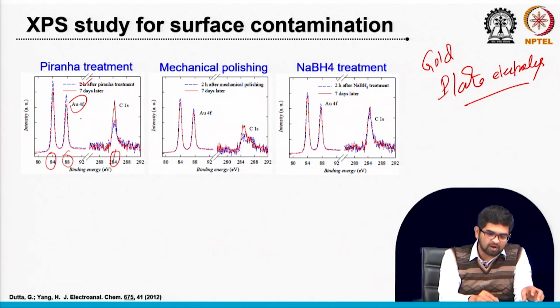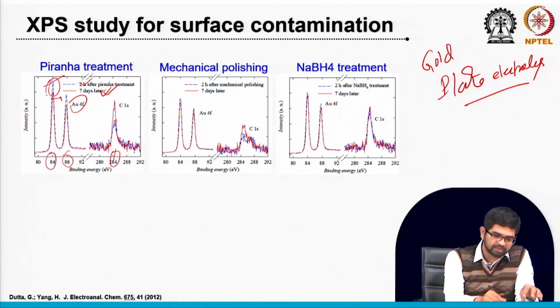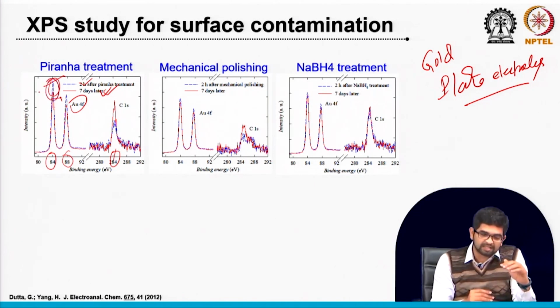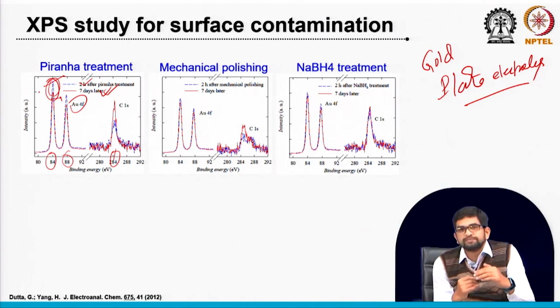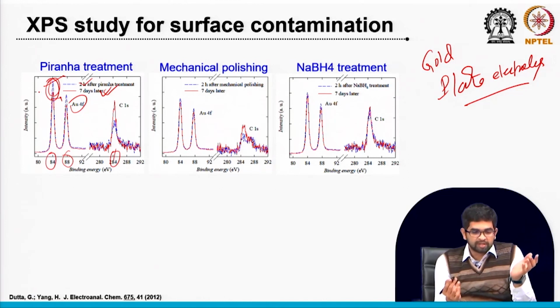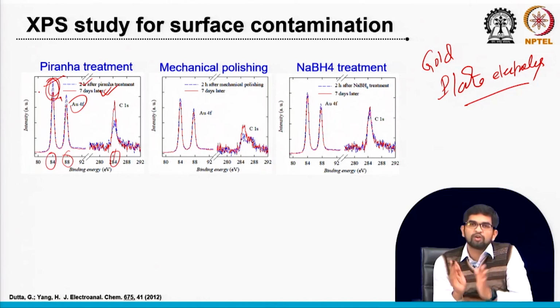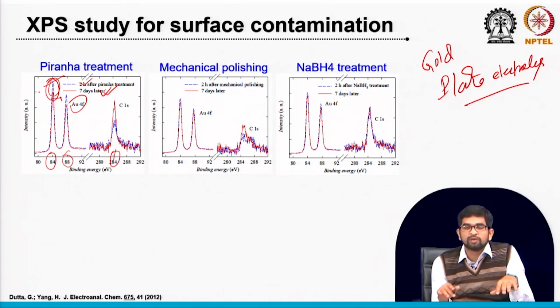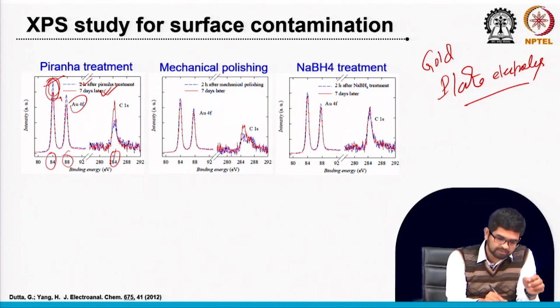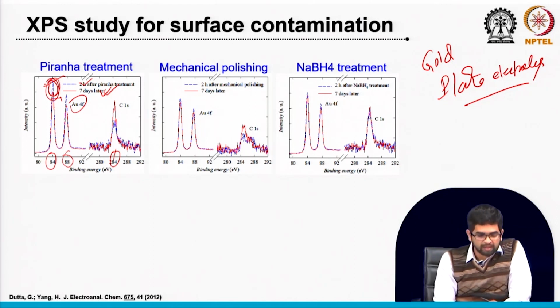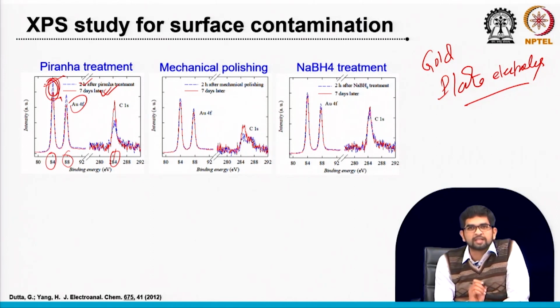You can see there is not that much change, but a little bit of change is still there after 7 days. Just after and after 7 days, you can see the gold peak decrease, right? It means the gold peak is covered, maybe some contamination is possible, because piranha treatment is a very strong cleaning method. It can clean almost all the organic contaminants from the surface, and when you store it for a longer time, like 7 days in the laboratory environment, this gold peak is somewhat covered. So we thought maybe this is due not only to the surface reconstruction, but also some contamination may come, right?